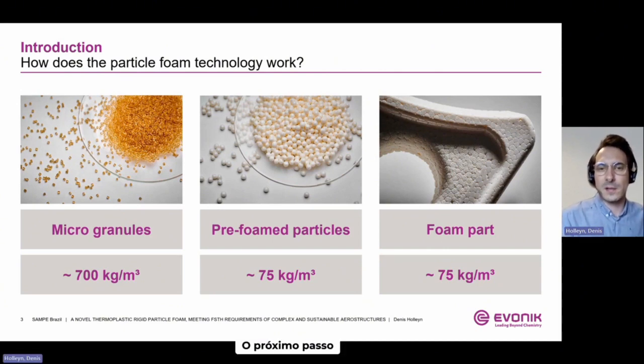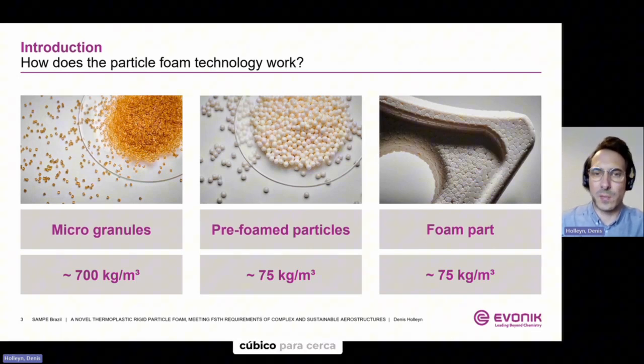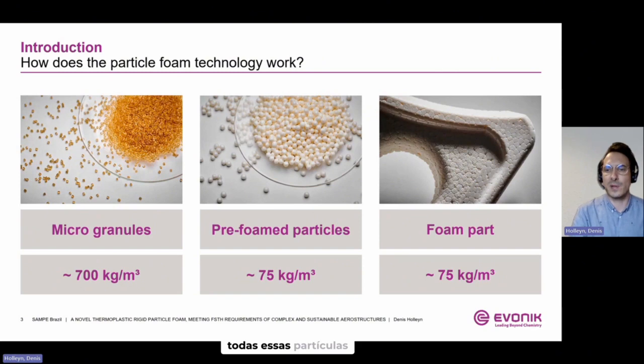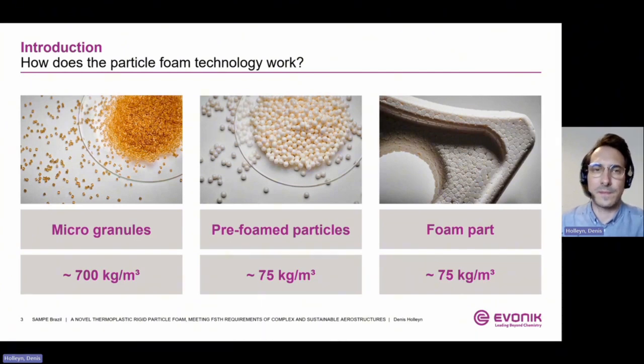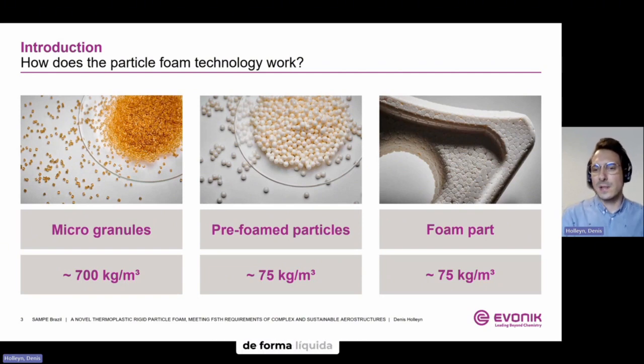The next step is the so-called prefoaming. In this production step, the microgranules are being prefoamed to small foam particles which contain a cellular structure inside. In this step, we also reduce the bulk density from, for example, about 700 kilograms per cubic meter down to about 75 kilograms per cubic meter. Ideally, all of those single particles have the same bulk density of, for example, 75 kilograms per cubic meter now. And in the last production step, the actual foam part process, these prefoamed particles are being processed to a net-shaped foam part, still having a low density of approximately 75 kilograms per cubic meter for the whole net-shaped part.